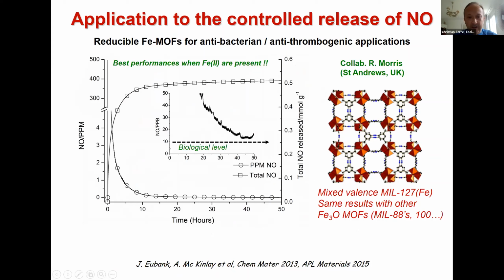You want a MOF that absorbs a large quantity but releases it very slowly, over not only hours but days. What they realized when comparing the pure iron 3 MOF with the mixed valence iron 2, iron 3 MOF is that the mixed valence, with the additional iron 2, allowed a much longer release of NO at the biological level. In the case of MIL-127, they could reach even 2 days of release at the biological level. They obtained similar results with other MOFs like MIL-88 or MIL-100.